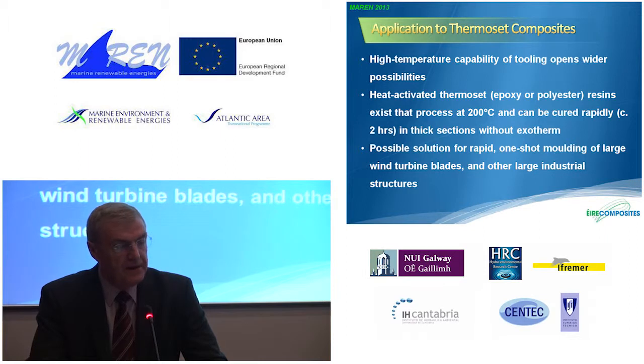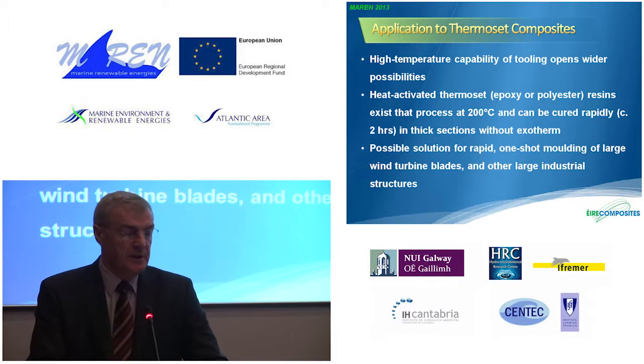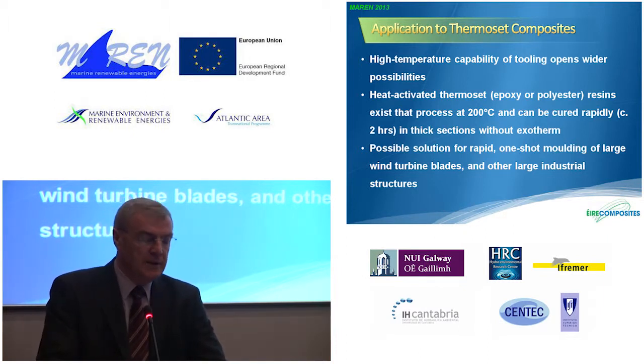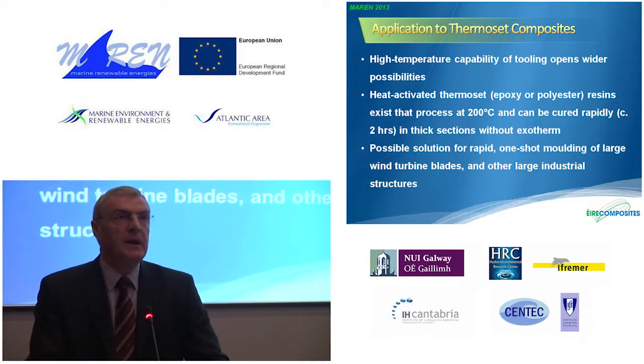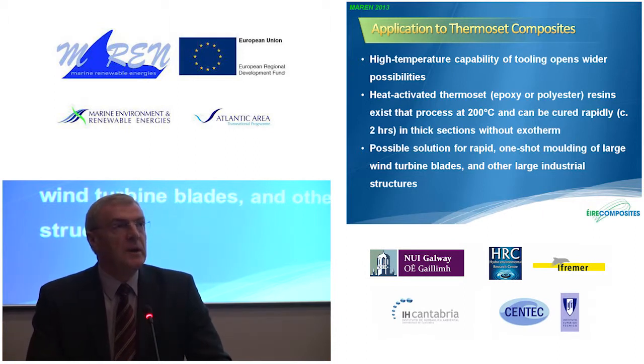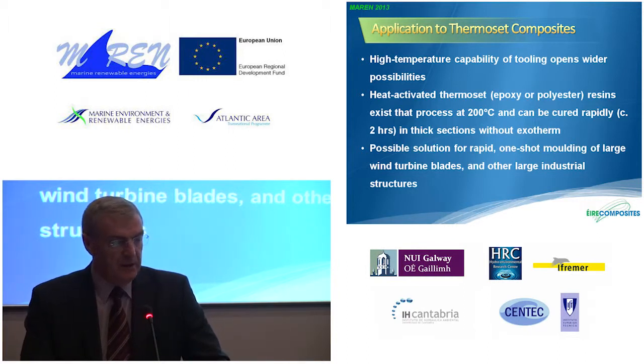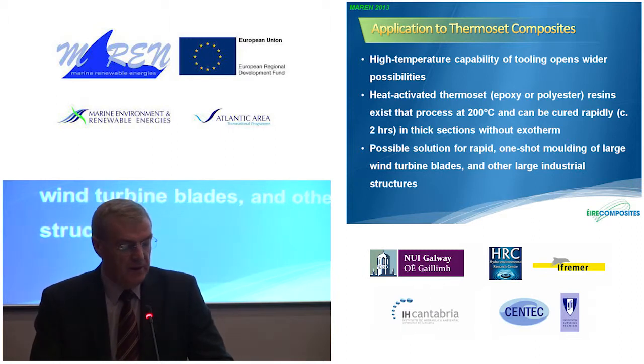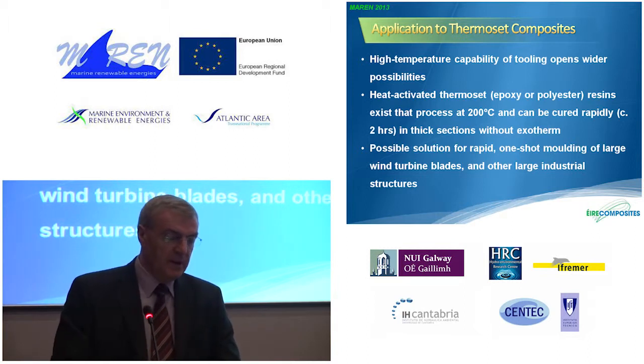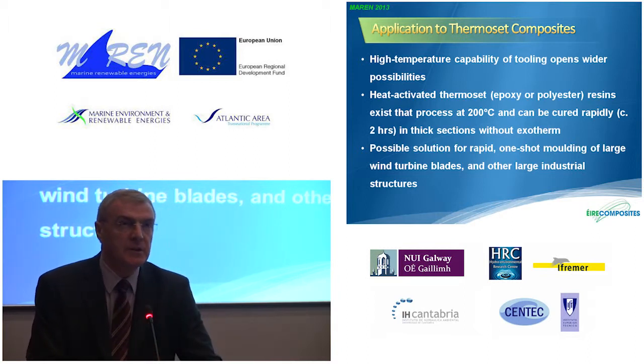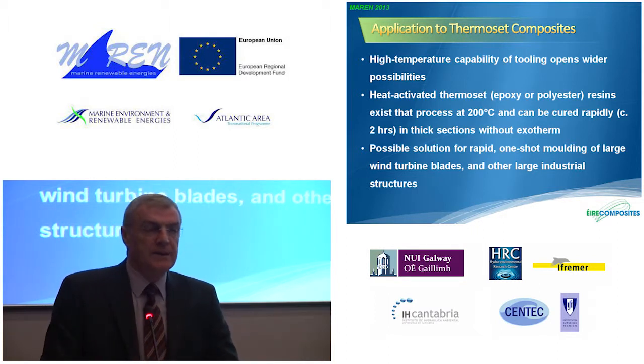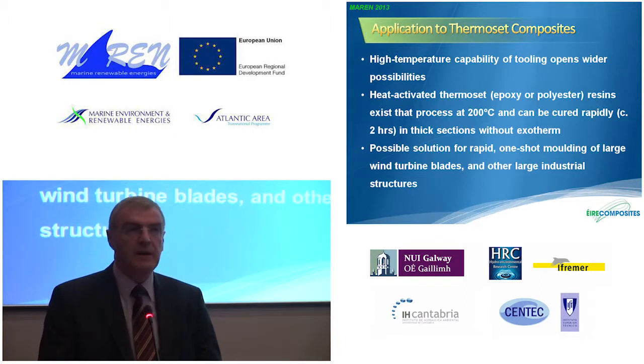The advantage of these materials is that they are heat activated rather than chemically activated materials, and therefore you do not have the same problem that you would have with standard materials where you have thick sections and you have an exotherm which you have to control. So it allows you to speed up the process. Also, the nice thing about it is that you have the possibility of making complex parts in one piece without having to glue or join. In the case of the turbine blades, we were able to manufacture the entire blade as one moulding rather than as several pieces, which is the norm in the industry right now.